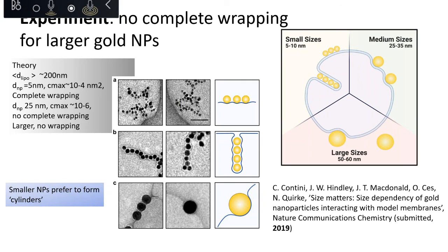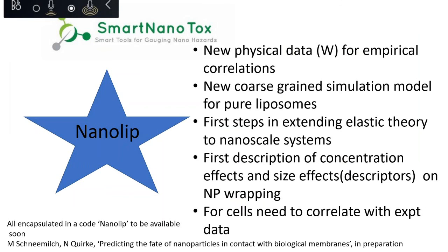These are Claudia's experiments with gold on liposomes, and our predictions are borne out. The small ones clump together to make cylinders. The medium and large only partially wrap.